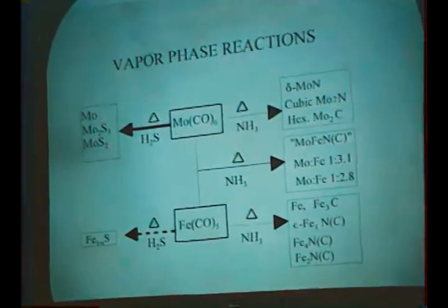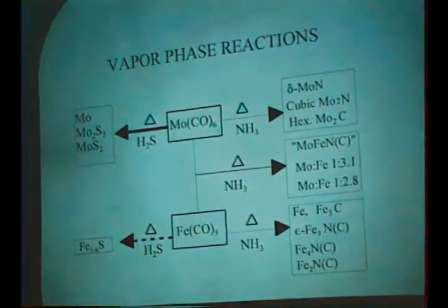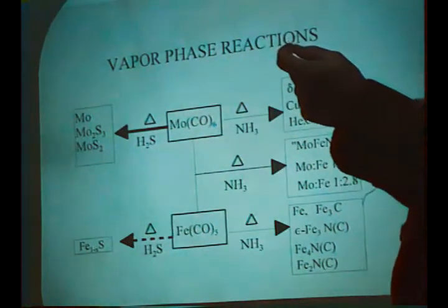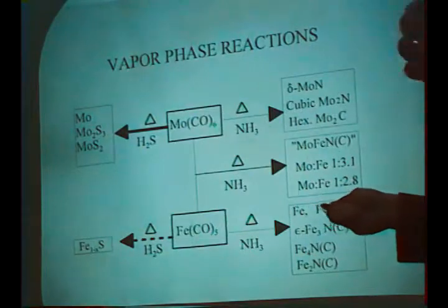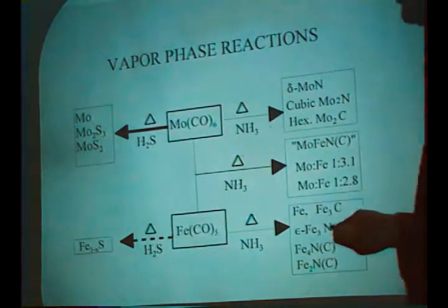Nitrides, this delta nitride phase, the hexagonal phase, the cubic form of molybdenum nitride, and also the hexagonal form of the molybdenum carbide. Going down to the iron compounds, the iron reacted with ammonia can produce a variety of carbonitrides. When the carbonyls are brought together in the vapor phase, prior to thermal decomposition, you can actually make mixed metal carbonitrides. And I haven't done this, but certainly mixed metal sulfides as well. We're going to be essentially right here today, just looking at one set of reactions, the molybdenum carbonyl reacting with hydrogen sulfide, going to the molybdenum sulfides.